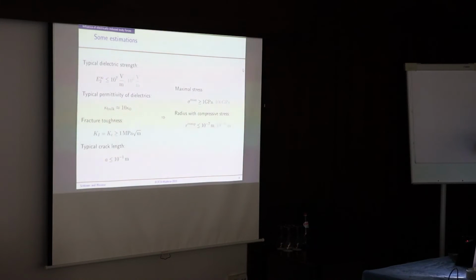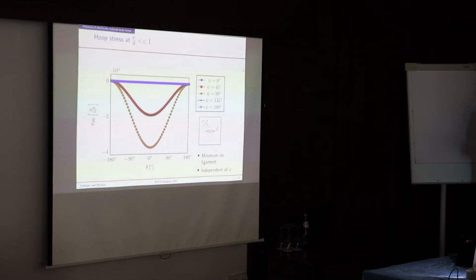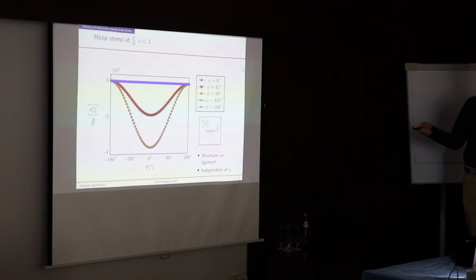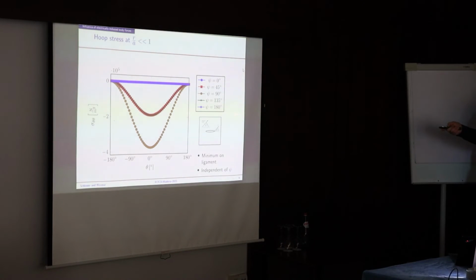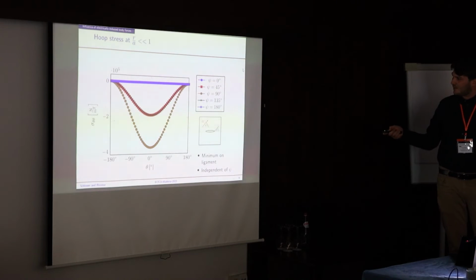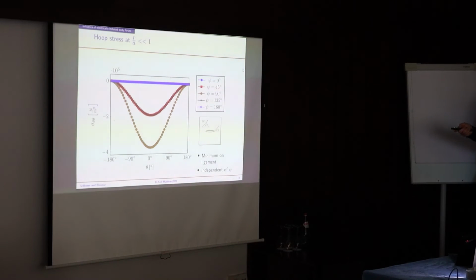So we were at the ligament till now. Let's look at the hoop stress around the crack tip to see if there's anything else happening, if you have tensile stress or something like that. But no, you always get, so this is the hoop stress around the right crack tip here, but it's the same as the left one, in the near field of the crack. And I changed this loading angle to see if something changes, but you see the curves are qualitatively the same. The minimum here doesn't move.